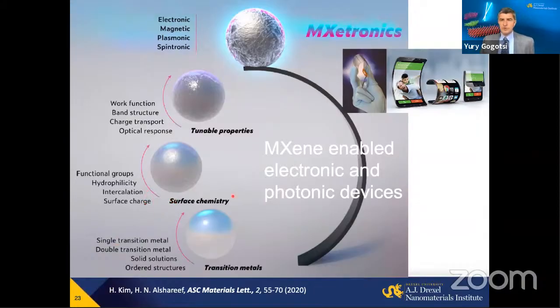Surface charge: actually, the majority of MXenes after synthesis have a high negative surface charge, between -30 and -80 millivolts, which makes them soluble here. Then there are the optical responses, tunable band structure, and also work function, which depends largely on the surface termination, and has been predicted to go from 2 to 8 electron volts, depending on surface termination and MXene composition. The variety of electronic, magnetic, and plasmonic properties really leads to the possibility to create entire fields of electronics, where MXenes can also work as current collectors.